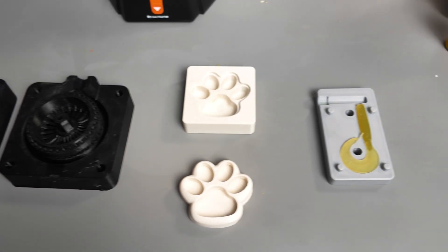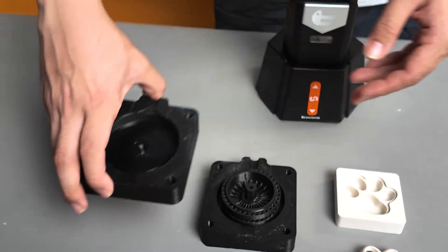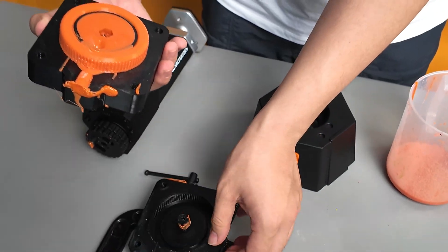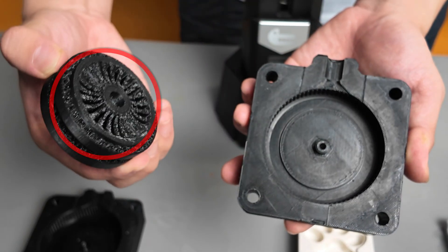Let's start with the mold material. For molds, we recommend PETG because it doesn't stick to soft PVC and allows for easy demolding. For any rigid structure you want to include inside or outside your product, we recommend ABS.